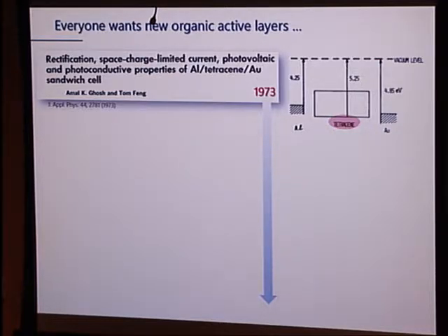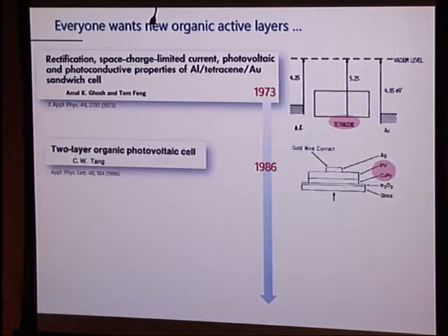This was sufficiently exciting that a lot of effort went into this, slowly at first, but there's a very famous paper by Ching Tang from 1986 where he showed that if you use not one organic but two different organic materials, whatever those two things are, and again, same structure, top electrode, bottom electrode, you sandwich them together, you get a solar cell that now is starting to be a little bit better, like 0.1 to maybe 0.5% efficiency, so that's already a couple orders of magnitude from misery into something that's still poor. However, the insight was that you needed to somehow manipulate the material that is the active matrix. And this has pretty much been the story for the next 30 years.